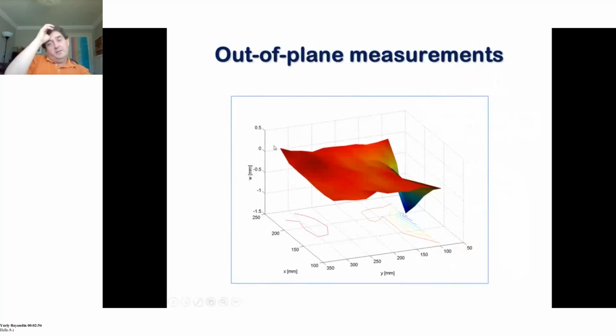And you can see that there's some forward displacement in lead because we've missed hitting exactly on the lead layer by about 0.5 millimeter or so. So we can see the shape produced by that impact within the target. So we're doing sub-millimeter displacement of a target that's tens of centimeters in size at a time resolution of around 10 nanoseconds. So we can really capture very small motions within the target.